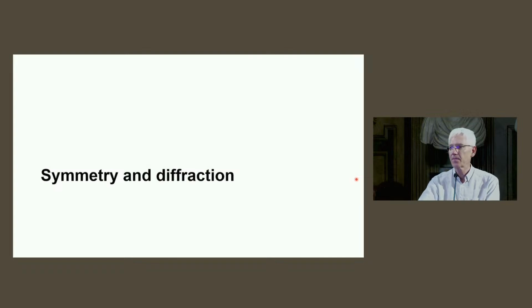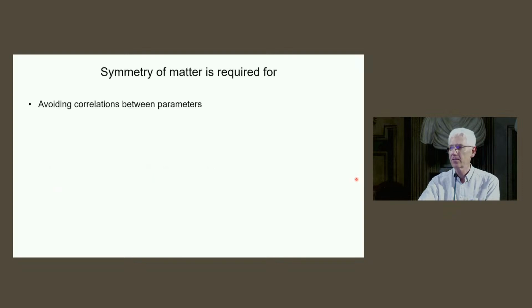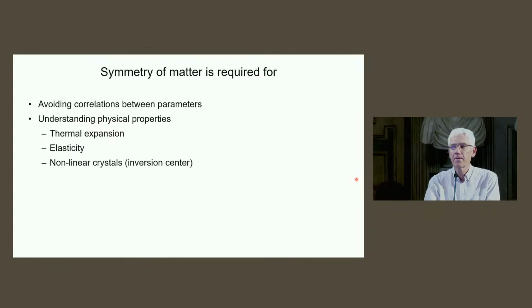Now let's go to the diffraction before we complete this analysis of the modulated structure. And diffraction and symmetry, so one can say, I don't care about symmetry. So why should I care about it? And the answer is very clear: to avoid correlation between parameters. And that's everywhere. So if you have thermal expansion, if it's equal along 2 directions of a cubic symmetric crystal, then it's equal by symmetry, and it doesn't make sense to try to accurately determine the thermal expansion along the A-axis and the thermal expansion along the B-axis, because they must be equal. And in most experimental techniques, if you ignore this equalness, you suffer from the problem that you have correlated parameters in your analysis, and the analysis doesn't work.